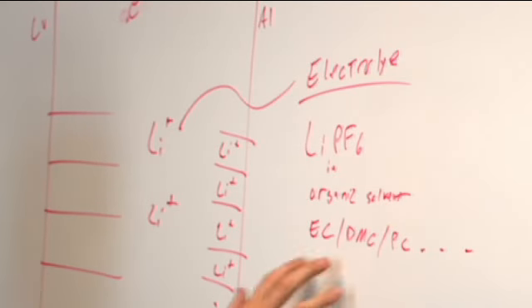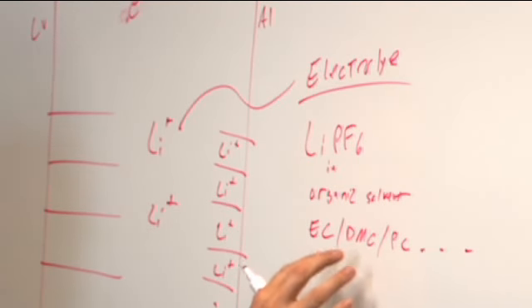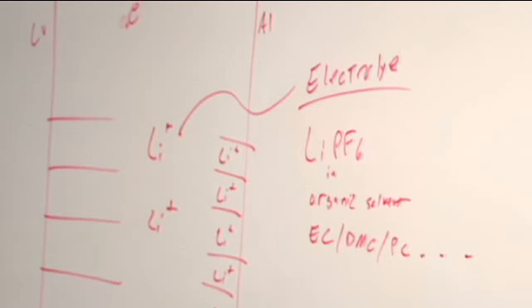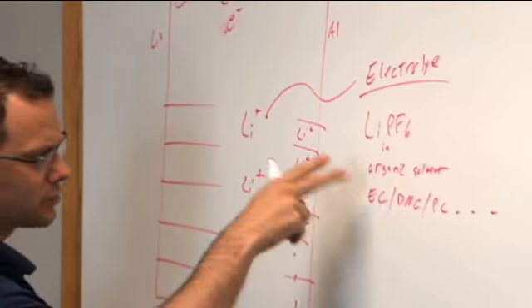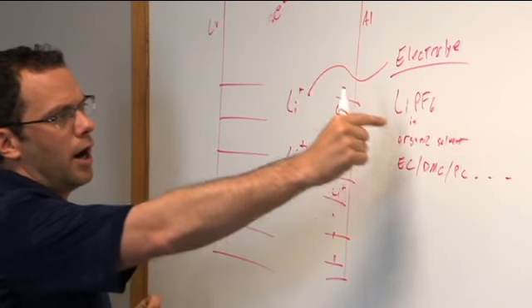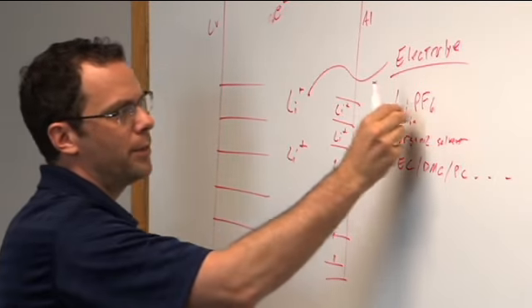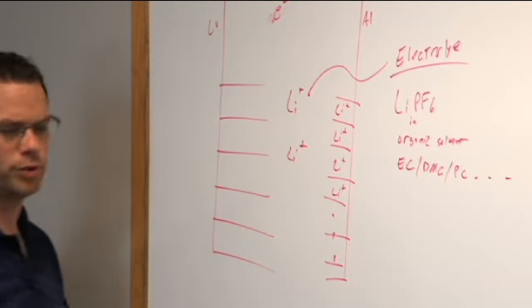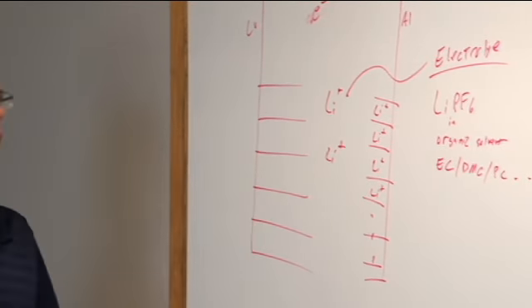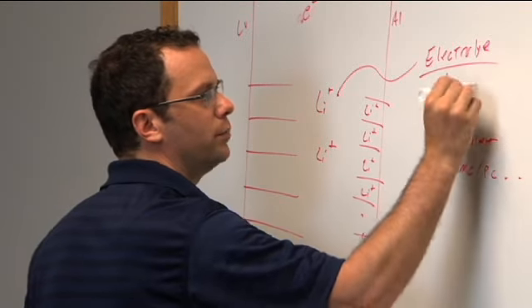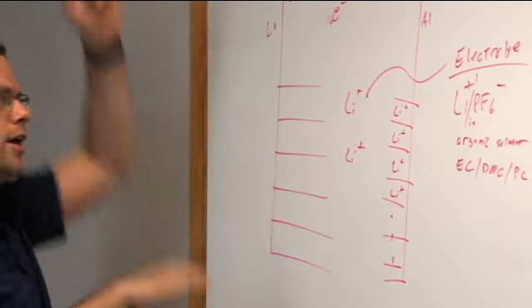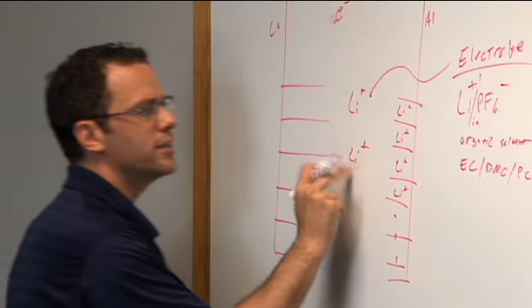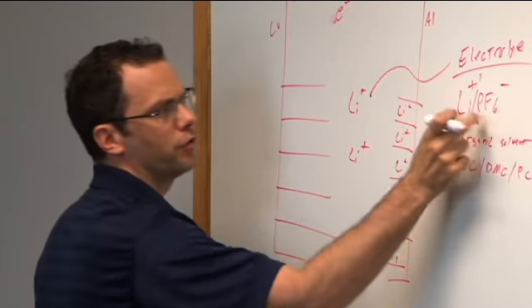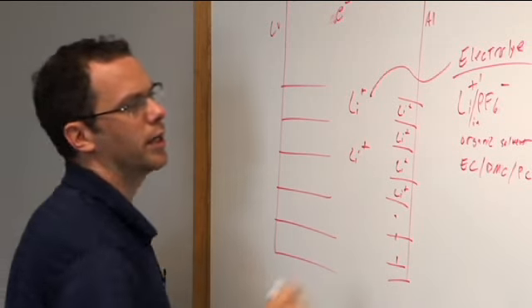It is flammable, and this is where some of the safety problems come with lithium-ion batteries. But the good news is that this stuff has no water in it. It's not water sensitive. You cannot have water if you're going to have lithium floating around. It's a bad combination, specifically if you're going to have any kind of lithium metal. But more importantly, when you drop in lithium hexafluorophosphate, LiPF6, in this organic solvent, it dissolves into Li plus and PF6 minus. So you've got this Li plus floating around and your PF6 minus floating around. And so this Li plus on the electrolyte comes from dissolved lithium hexafluorophosphate in this organic solvent, okay?